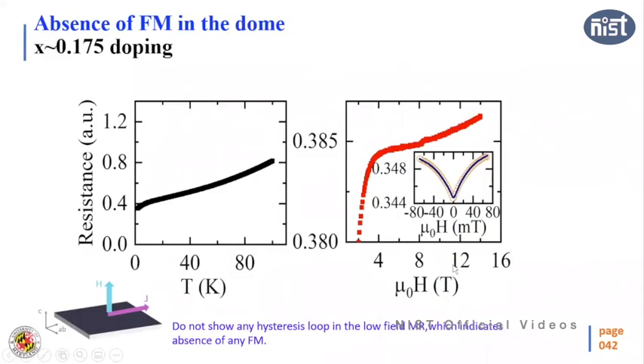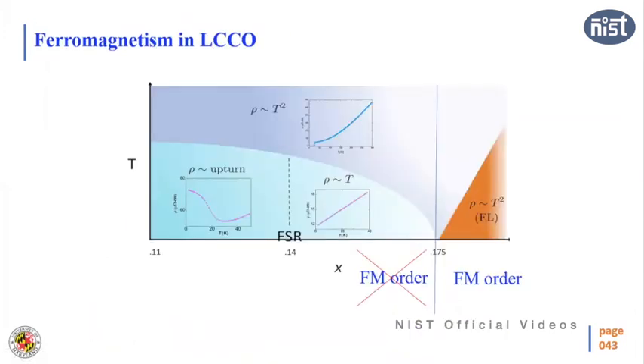Then we further wanted to confirm that there is no magnetism in the dome. So we grew one sample very close to the end of the dome. There is a TC, and the TC is below 1 Kelvin. So it gives us the temperature at which we can check if there is any kind of magnetization or magnetic loop. We did not find any magnetism. That suggests that there is no magnetization. So what we found in this material is that in the dome there is no ferromagnetic order, but out of the dome, if you dope this material beyond the superconductor, there is ferromagnetism.